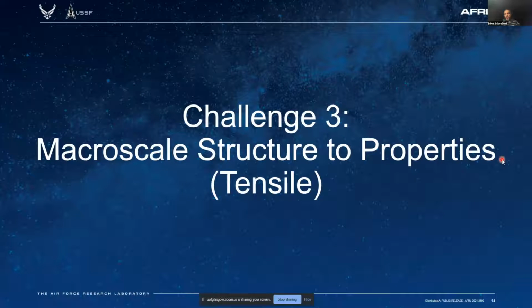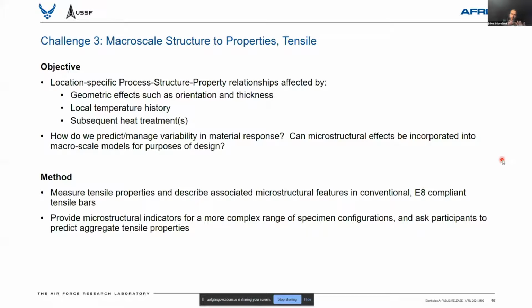Switching now to the structure to properties type questions and going back up to the macro scale, here the focus was on trying to predict tensile behavior of, I'll call them bulk type structures, given information about the microstructure. So we're not giving processing information anymore. We're not asking people to make predictions about the microstructure. We're basically, in this case, going to define: this is the microstructure that we observed after printing these components. Please make a prediction of what you would anticipate the tensile behaviors to be.